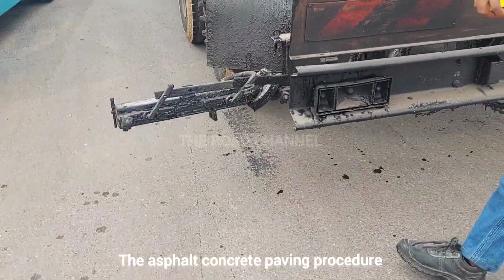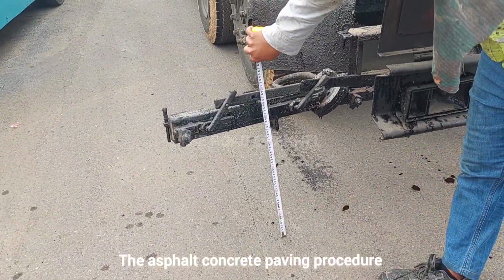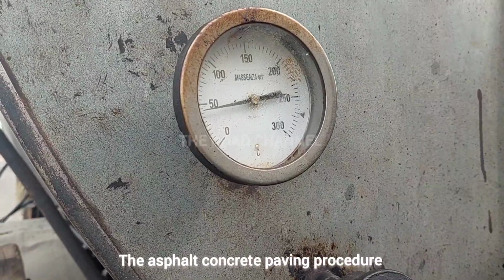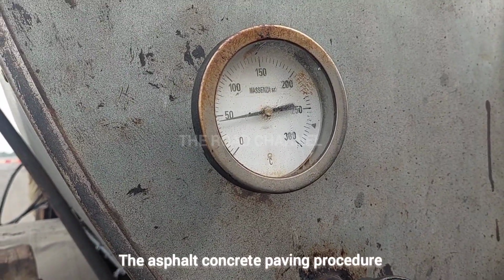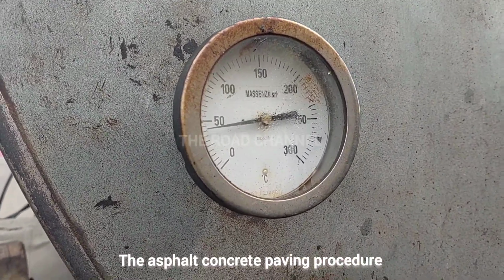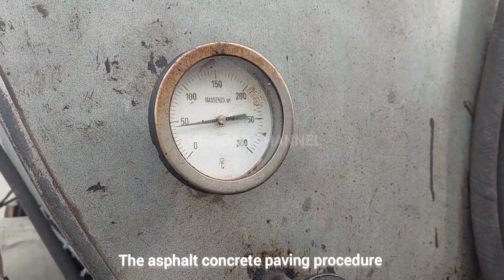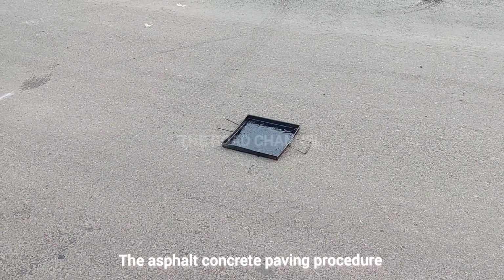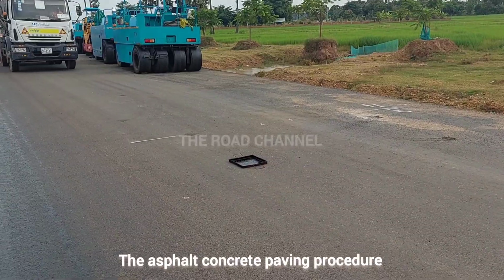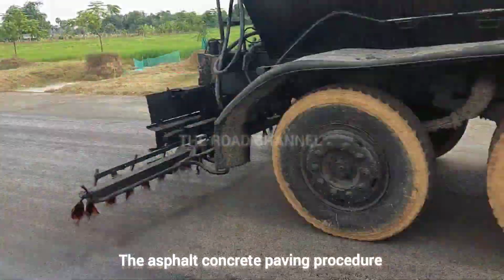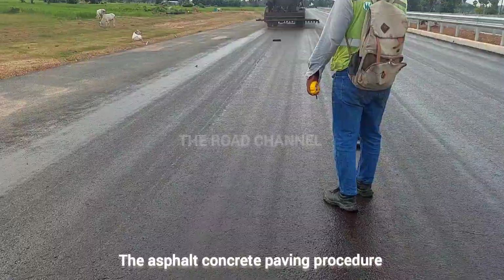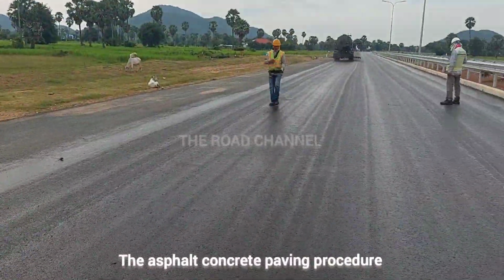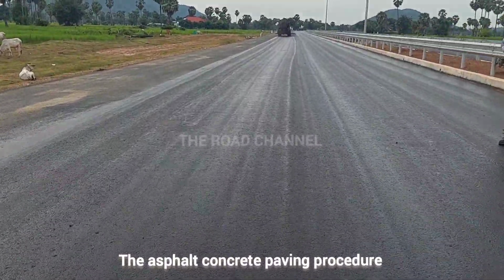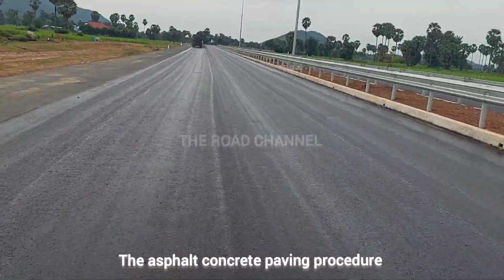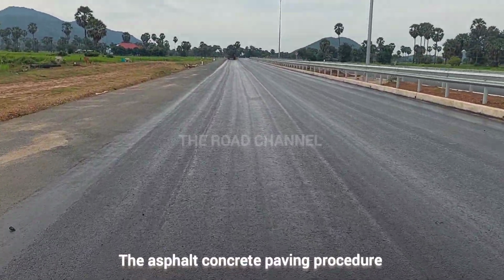1. Preparation. Site inspection. Ensure that the base course, such as compacted aggregate or existing pavement, is properly graded, compacted, and free from debris. Cleaning and tack coat application. Sweep the surface to remove dust and apply a tack coat, bitumen emulsion or cutback asphalt, to ensure bonding with the binder course. Material inspection. Verify that the asphalt binder mix complies with the approved job mix formula.